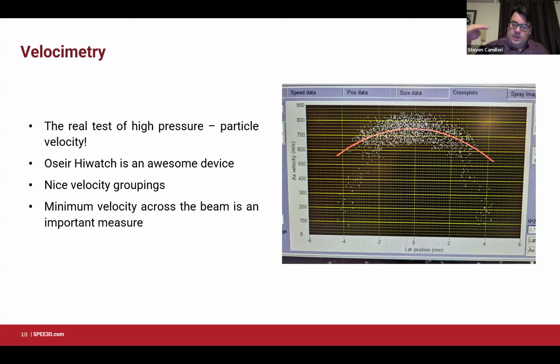You can see down the bottom of that chart there's a position across the nozzle. We've sectioned the beam with the particle velocimetry, and all those white dots are the particle velocities, and the red line is a group average through there. Our nozzle's exit diameter, for reference, is about 6.5 millimeters, which is pretty much precisely where those particles are clustered. So indeed, the nozzle's doing a good job, and the Oseir HiWatch is doing a good job. Fantastic results, I think. I'll present some more detail on those now.